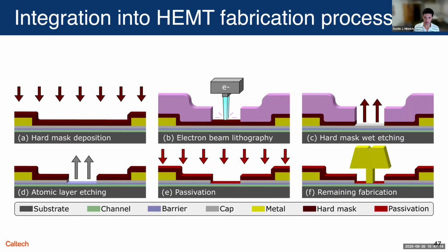All right, so this is kind of approximately how we do the flow. The only difference, if you're kind of expert in this, is we need a hard mask for the atomic layer etching because it's in this plasma, or rather it has these hydrogen radicals which will attack the resist, so you need a hard mask. But otherwise, it proceeds pretty similarly to what you might be familiar with.